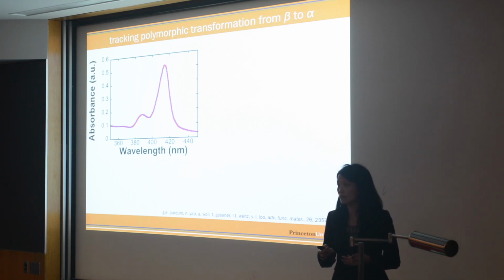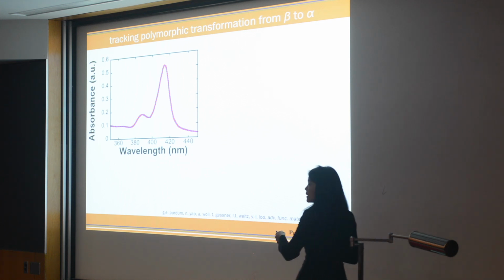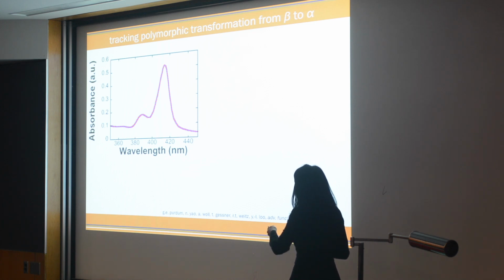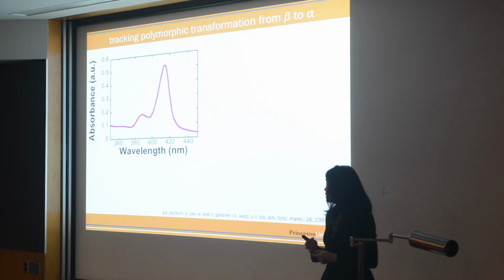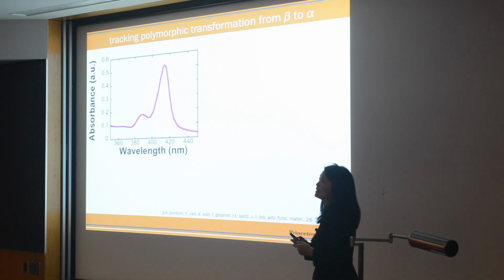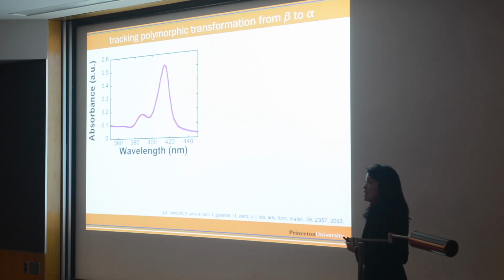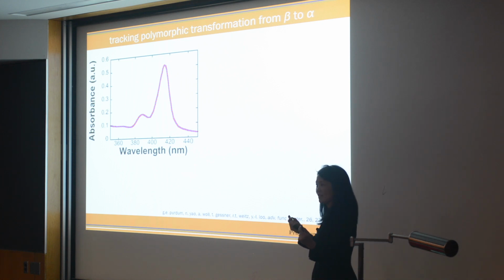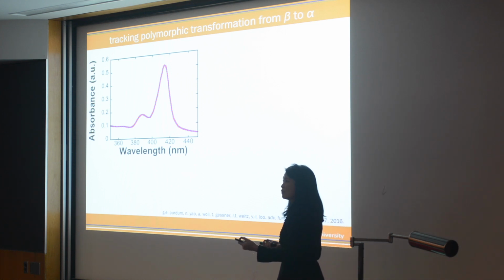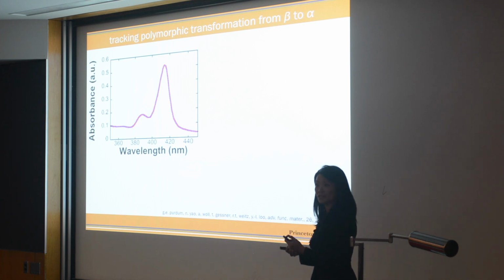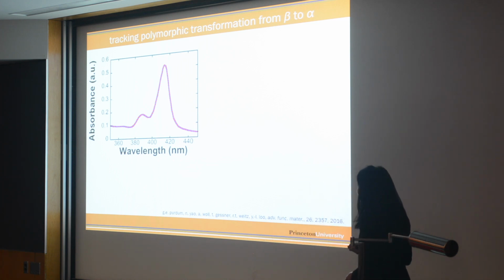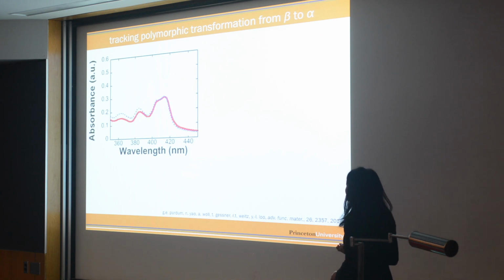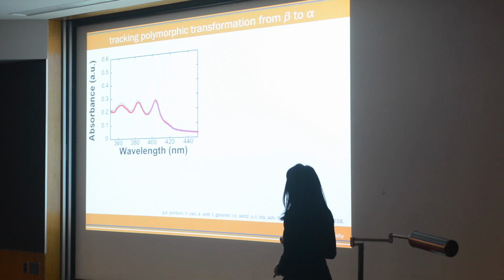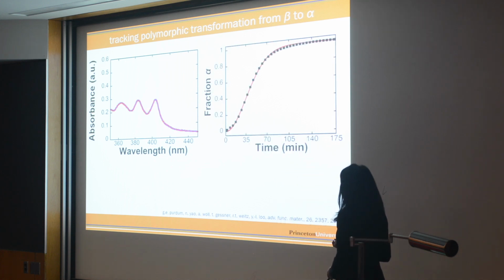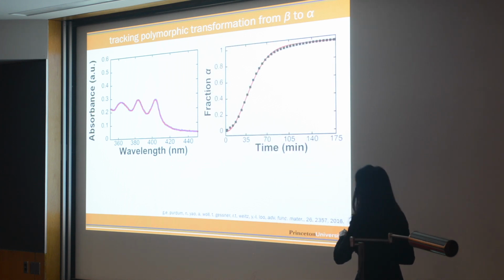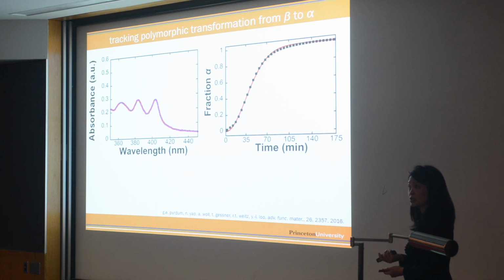What I'm going to show you is quantitative data on this transformation process when we expose the beta phase to solvent vapors. This is the UV-vis spectrum of the beta phase, that's in red. And the blue is our calculated spectrum. This calculated spectrum is basically a weighted function of the alpha phase data and the beta phase data. If we track this weighted function, we can track how much is being converted as a function of time. So during solvent vapor annealing, you convert to the alpha phase. If you track the weighted function, that's fraction alpha as a function of time, we get kinetic data of this transformation process.